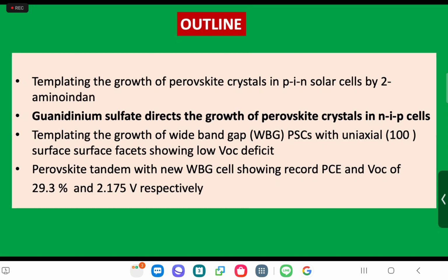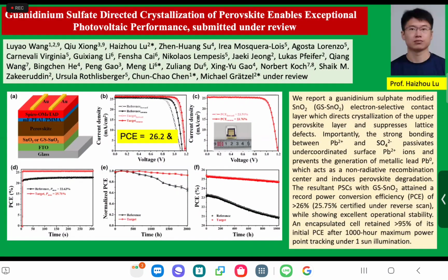can get that growth. But I should mention to you, actually, the experiment was done with a two-step method. We first put down the lead iodide, and then it's converted. Okay. So what is really directed by this surface-adsorbed guanidinium sulfate is the formation of the lead iodide, which is really coplanar. And there are two reasons for that. I'll explain to you in a minute. But as a result, we get much better efficiency and also stability-wise.